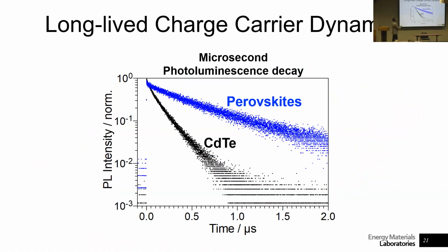And so if we compare cadmium telluride, a traditional semiconductor for solar panel manufacturing, made by collaborators who made really high quality cadmium telluride at really high temperatures in very impressive facilities, you can see the lifetime of electrons. That tells us how long an electron can be in a material before recombining. The lifetimes are within 1 microsecond. In perovskites, with a much more rudimentary setup and a lot of impurities, we have lifetimes that are even longer than what cadmium telluride has. Silicon, with the amount of engineering that we've done to it, has microsecond range.